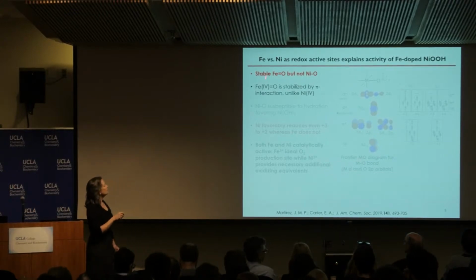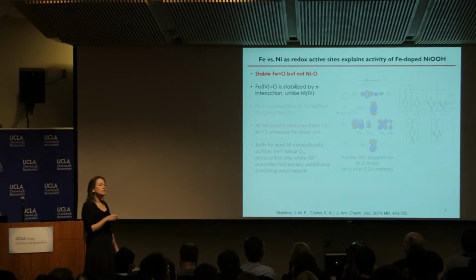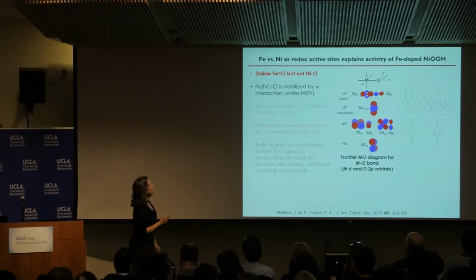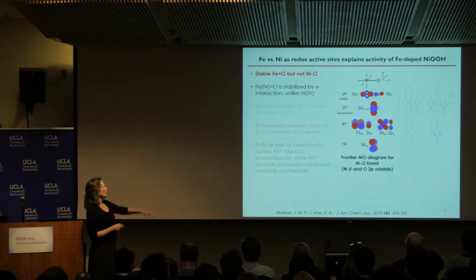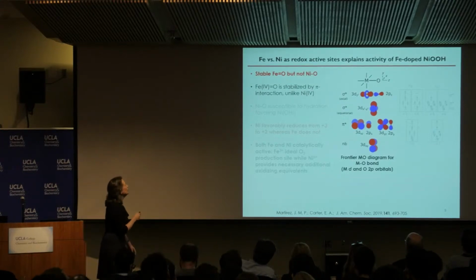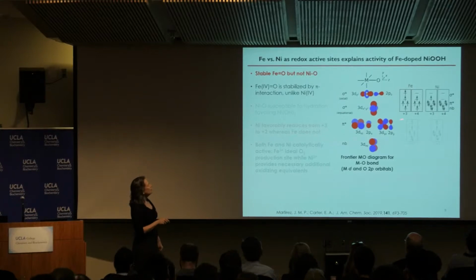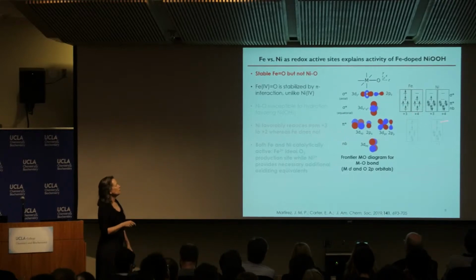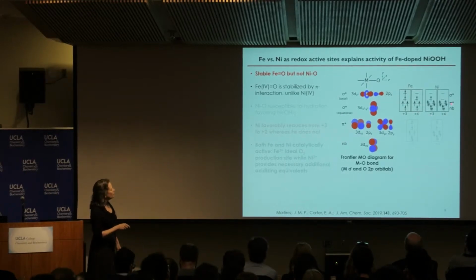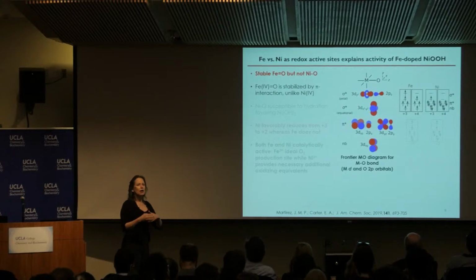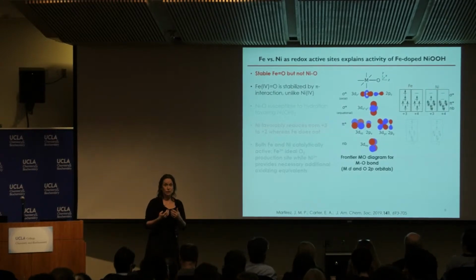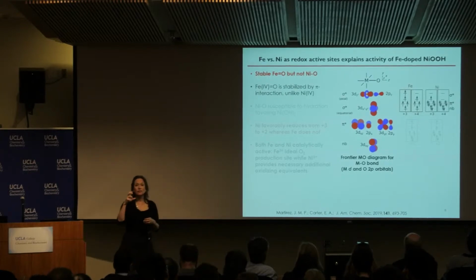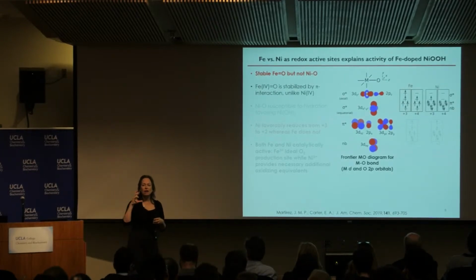What it has to do with is that you can make, as I've already said, an iron 4 oxo, but you can't make a nickel 4 oxo. Why is that? Well, here's a simple molecular orbital diagram. I'm not going to go through why that's the order. That's crystal field theory. And now let's just look at the occupation of an iron 3 plus ion, an iron 4 plus ion versus nickel 3 plus and nickel 4 plus. And these, by the way, these occupations, they're not just arbitrary. These come out of the electronic structure calculations where we can calculate the magnetic moment on the ions. And so that tells us how many unpaired electrons are present.